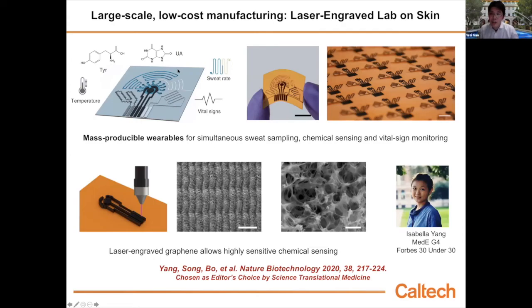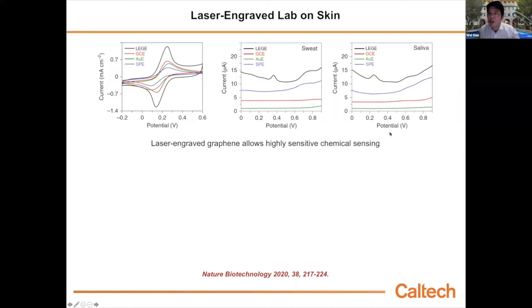Basically, the entire multimodal physical sensor, chemical sensor, and microfluidic module can be fabricated using a simple laser engraving approach. As you can imagine, it could be fabricated at very large scale and low cost. And this graphene-based biosensor shows very good performance compared to classic electrodes. You can see the much higher oxidation-reduction signal compared to a typical gold electrode, screen-printed electrode, or glassy carbon electrode.